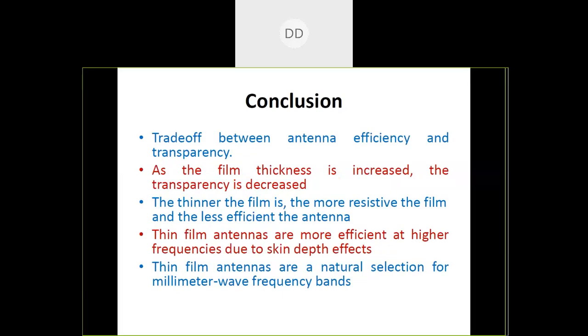But in the case of designing optically transparent antennas, the use of TCO involves challenges which we need to address using a reasonable trade-off between antenna efficiency and transparency. So we have discussed that as the film thickness is increased, the transparency is decreased, and so the thickness must be minimized. But the thinner the film is, the more resistive the film is. So the less efficient is the antenna. These are trade-offs which we need to address.